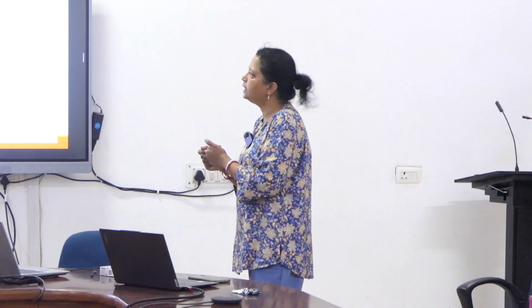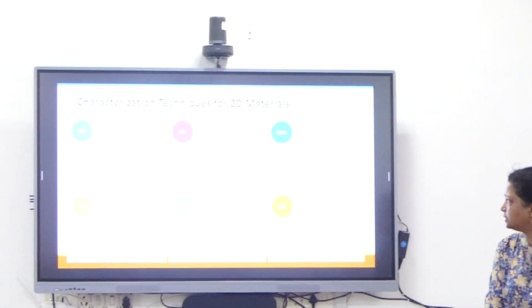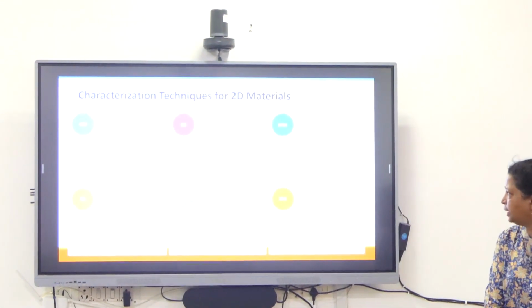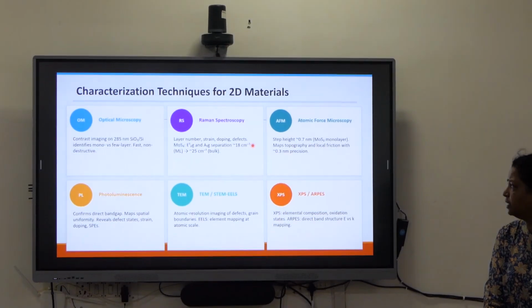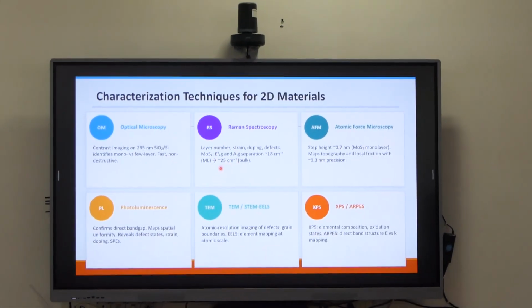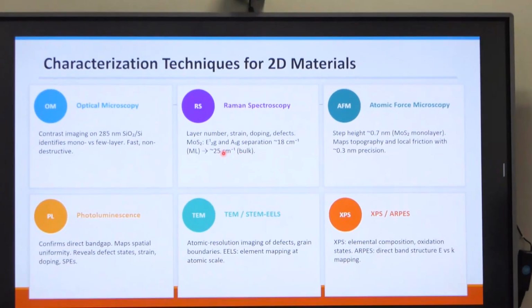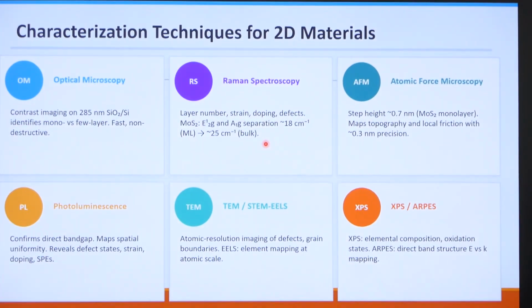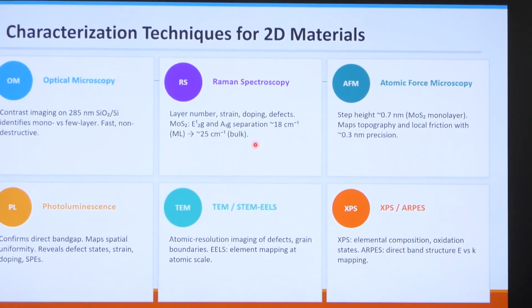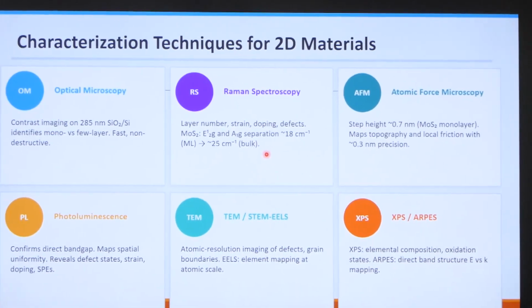There is an example: a particular peak here tells you whether it is MoS2, two-dimensional molybdenum disulfide. If the separation between the two peaks is 18 inverse centimeters, then it is a monolayer. If it is 25 inverse centimeters, then it is a bulk form. So from that one can characterize whether it is formed or not.